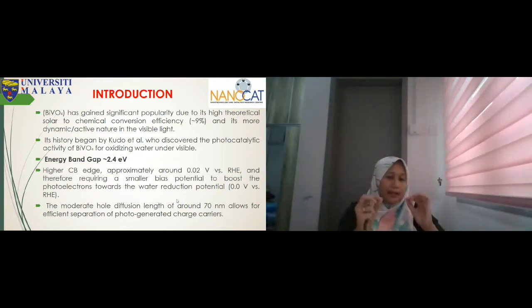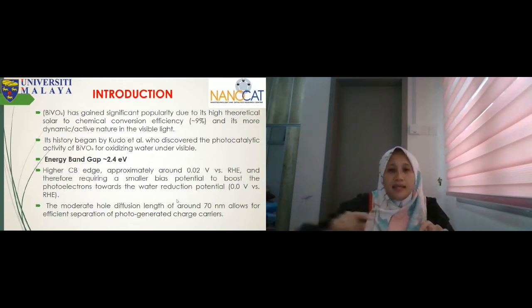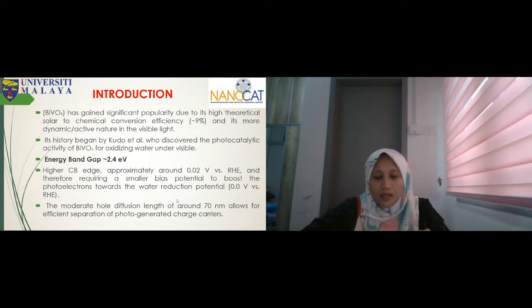In a semiconductor, the band gap is very important. For electron movement, bismuth vanadate is special because it has a higher CB edge, approximately 0.02 V versus RHE, and it requires only a small bias potential to boost the photoelectrons toward water reduction. The last uniqueness of this material is that it has a moderate hole diffusion length of around 70 nanometers, which allows efficient separation of photogenerated charge carriers. This is the introduction of the material and why I chose it.